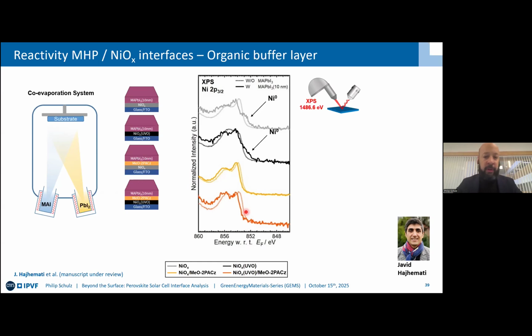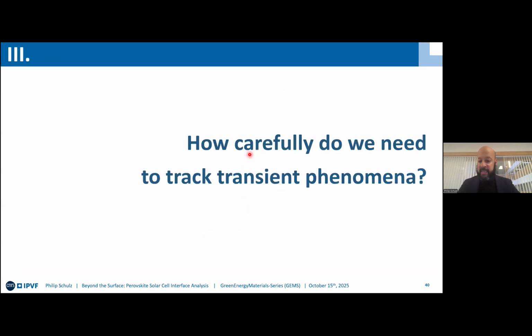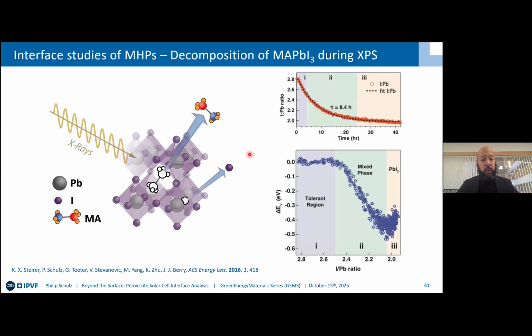Even though its optoelectronic activity seems to be different, it does not seem to lead to a lot of recombination, as photoluminescence actually does not change a lot, even if you have this metallic nickel compared to the other cases before with the tin precursors. Okay, so all nice and well.